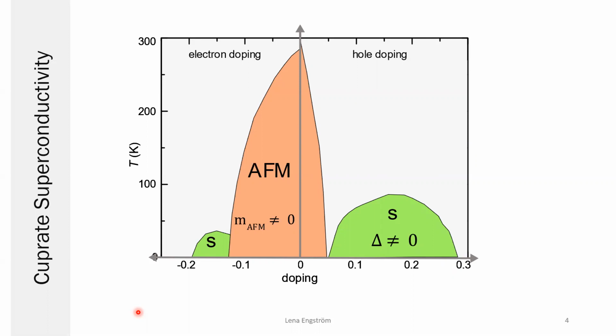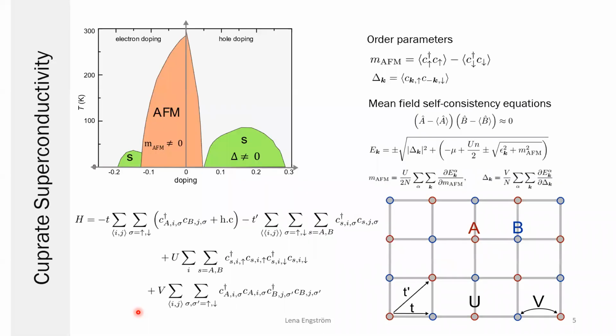So we want to look at the simplest possible model to reproduce this phase diagram. So this simplest effective model that we have then can be this Hubbard model here, which is the t-t'-U-V model. So we have a square lattice because the cuprates, like the iridates, have perovskite structure where we have these basic quasi-2D layers of this square lattice. So what we consider is that we can have hopping between nearest neighbor sites. We also must include next-to-nearest neighbor sites because this gives this asymmetry between the electron-doped and hole-doped state, which we just know from experiments should be there.